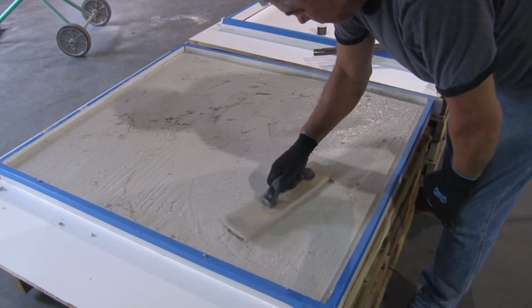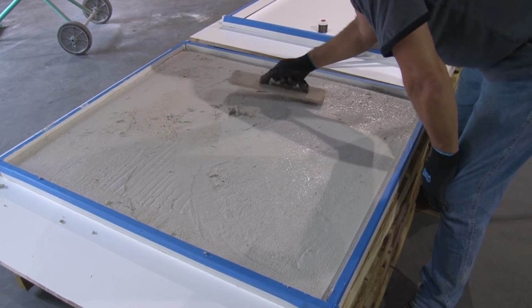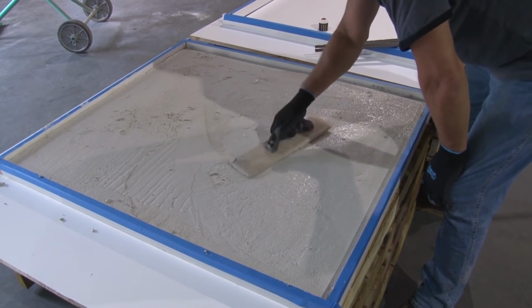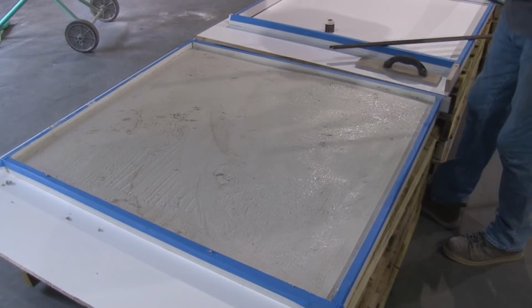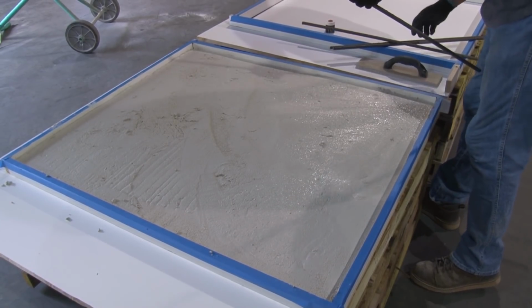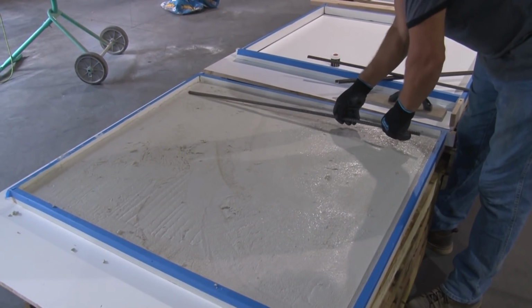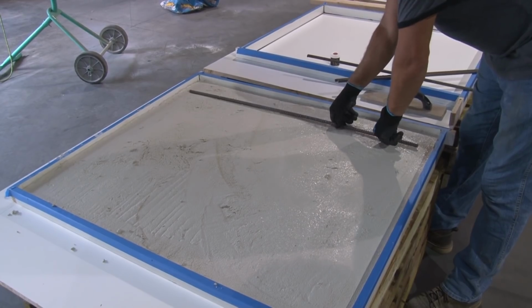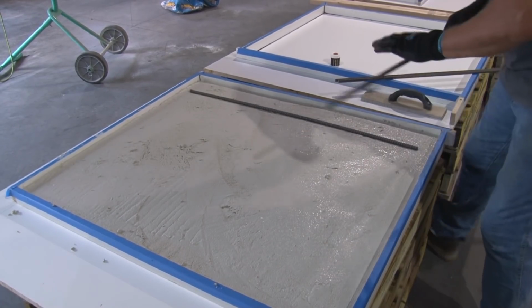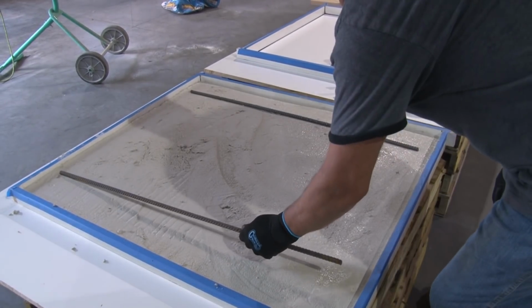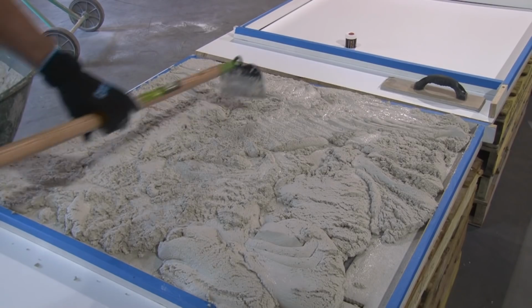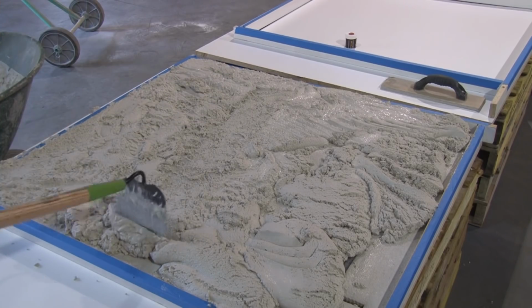Complete the pour in 2 equal lifts, about 1 inch deep. Work from the bottom up, rather than side to side. This will minimize any surface color variations. If necessary, structural steel should be embedded after applying the first lift. Then continue placing the mix, overfilling the form slightly.